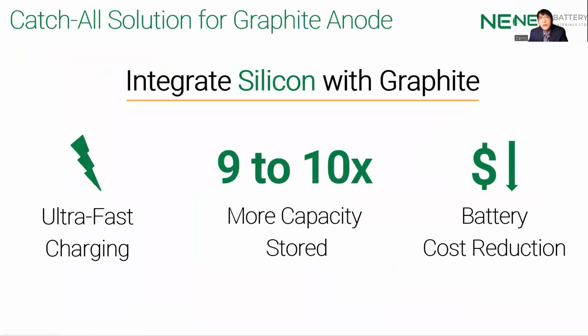But what if we can tell you that there is a secret ingredient or mineral that can alleviate all three problems? And this is integrating silicon with graphite into the anode material. Let me highlight some benefits of using silicon in the battery. First, we can enable ultra-fast charging if the silicon anode is manufactured right. Second, 9 to 10 times more capacity, which determines the runtime of the battery, can be stored compared to graphite in the same volume or weight. And lastly, the whole battery cost can be reduced, as smaller amounts of silicon can give higher performance, longer ranges, and faster charging than graphite itself.